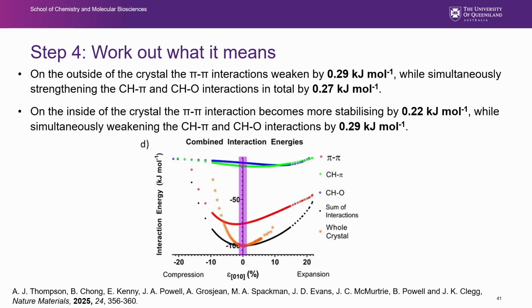So we can work out ideally what this means. Again, there's lots and lots of data points here, but the key thing to look at is comparing the slopes of the green and the blue compared to the red interactions. You'll see that the blue and the green slope down this way to the right, whereas the red slopes back the other way. That means on the inside of the crystal, the red interaction is storing more energy compared to the outside of the bent crystal, where the opposite is in fact occurring for the blue and green interactions.